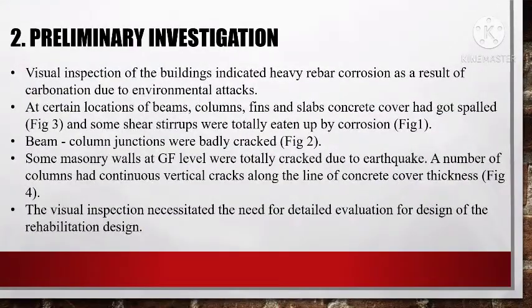For the rehabilitation work, preliminary investigation is done. Visual inspection of the buildings indicated heavy rebar corrosion as a result of carbonation due to environmental attacks. At certain locations of beams, columns, fins and slabs, concrete cover had got spalled and some shear stirrups were totally eaten by the corrosion. Beam column junctions were badly cracked.